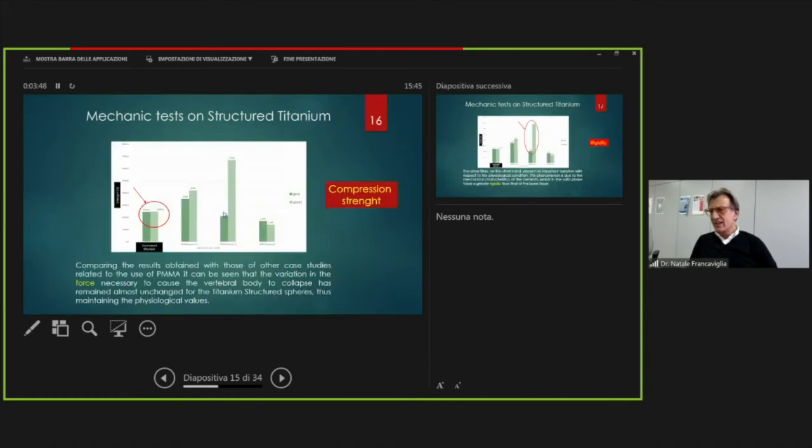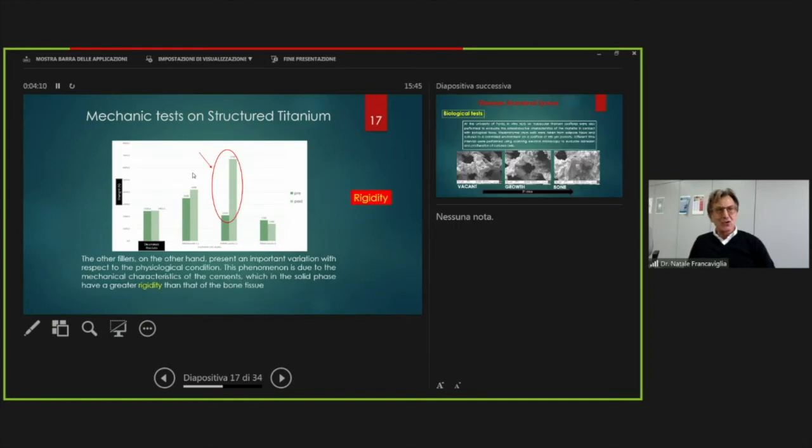The compression test before and after the technique shows that the vertebral body can maintain compression stress similar to a normal vertebral body, and the rigidity is similar to a normal vertebral body, versus polymethyl methacrylate, which gives a big rigidity to the vertebra.